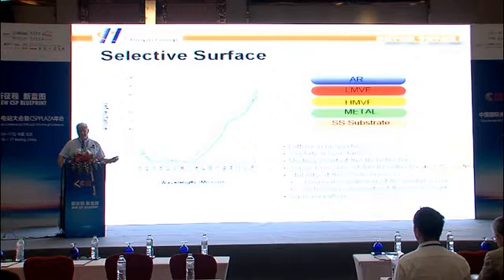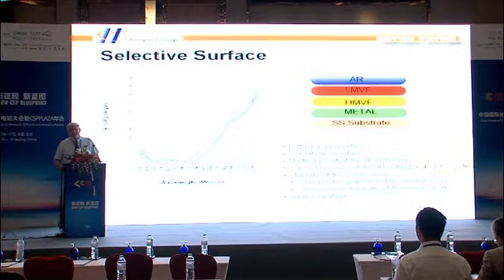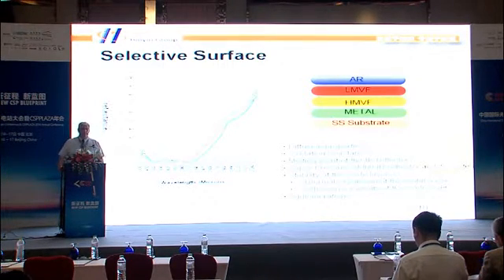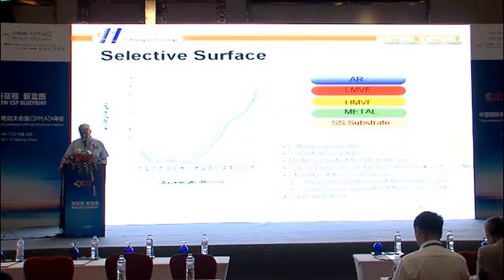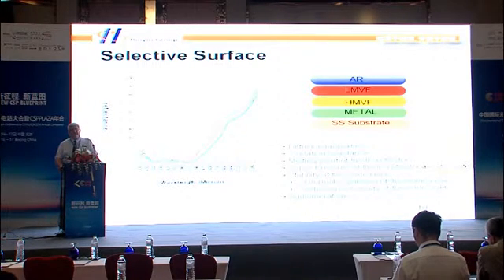If we look at lowering emissivity, we can also use different metal infrared reflectors. Probably the best one is silver, but it's not easy to stabilize. After that will probably come aluminum, but that will not last much above 400 degrees. Then you have molybdenum, tungsten, and nickel comes somewhere. So these are the materials that are available. If you go to very high temperatures, you're going to find yourself with very exotic materials like platinum and stuff. There are a lot of conditions required on these materials.